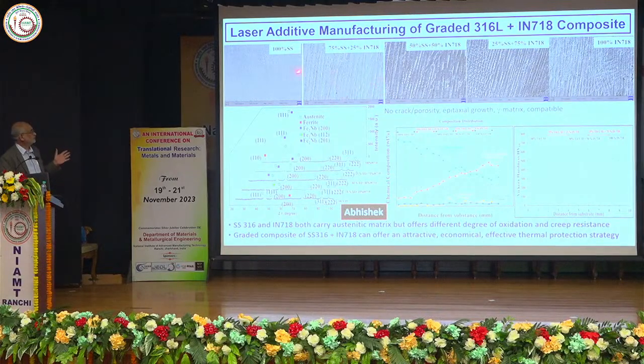So then, borrowing from this, we said, why not take stainless steel and end up with a superalloy? Not necessarily a turbine blade, but there are many components - let's say a heat exchanger. If I have a pipe or tube which is stainless steel, and I make a clad with superalloy, doing it with a sharp interface from stainless steel to superalloy makes the interface amenable to cracking because of compositional mismatch. How about doing it in graded composition - 25%, 50%, 75%, and then complete superalloy? That's the idea, and this is in progress.